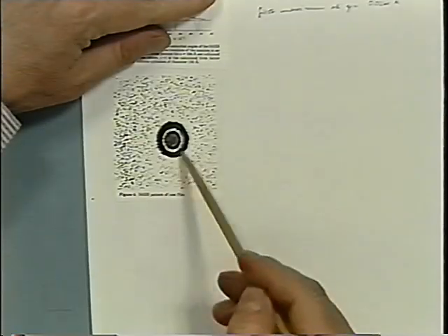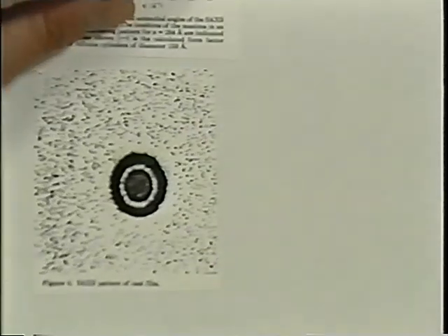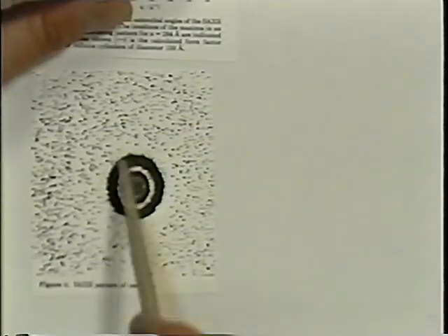You can measure that pattern in circular. Here it's an isotropic sample because the grains are really ordered regularly in all directions. So you're getting really circles in this case. It's the initial sample, as cast, has regular morphology, phase separated, and that's the starting point of things we are going to look at.